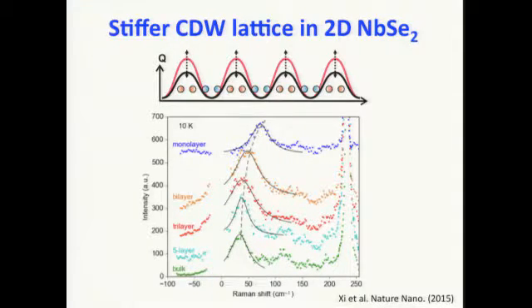And somewhat surprising is actually that when you go to the monolayer limit, you can see that this mode actually gets blue shifted, meaning that actually the CDW lattice is stiffer. So it's actually representing a stronger CDW order. This is a somewhat counterintuitive result, which I will not discuss the mechanism too much.